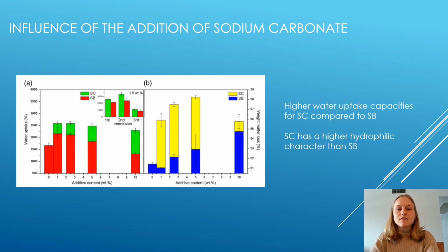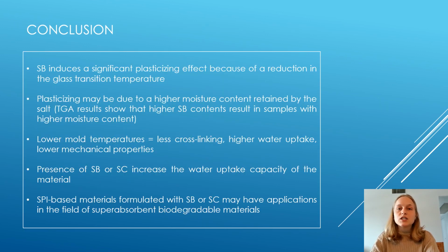They then evaluated the effect of adding sodium carbonate to the blend. The results showed that the water uptake was higher for samples containing SC compared to SB. This could be a result of the higher hydrophilic character of SC. In conclusion, the addition of SB to the protein-based matrix creates a plasticizing effect, which might be related to the higher moisture content retained by the salt. The presence of SB in the polymer makes it more easily deformed with a lower Young's modulus and with a greater number of pores.